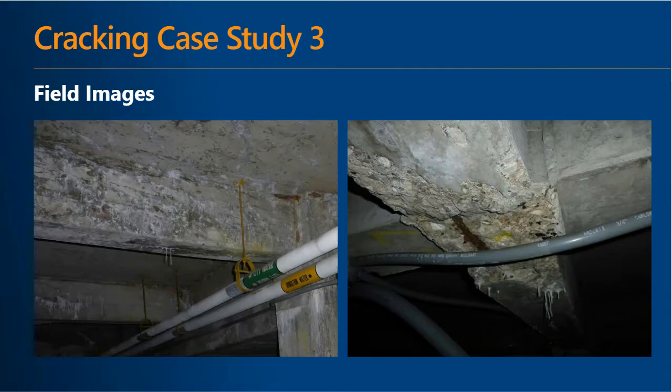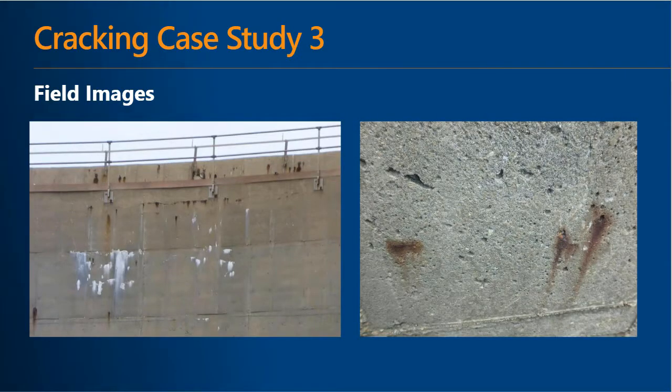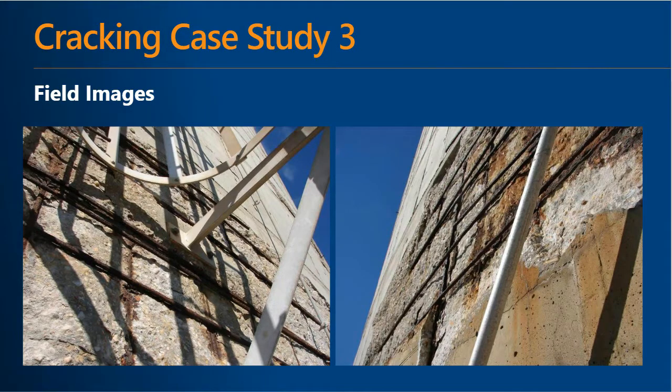Essentially, you have these horizontal cracks with deposits. And another example in the field may look like this, where you again have these horizontal cracks. In this example, you again have two deposits, one that's white colored and another red-brown color coming out of those cracks themselves. And as your cracking and deterioration advances, you may start getting spalls and loss of concrete cover to the point where you may be exposing embedded reinforcement that then can be susceptible to corrosion itself.